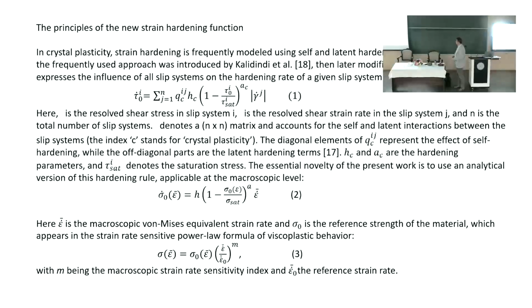And how do we go further? Well, this is not yet good because it is also a rate equation, and because this is an empirical function, we can try to integrate it. But before integrating, I would like to show that this function doesn't show the strain rate sensitivity effect, which is known in metal behavior, especially when you increase the temperature.